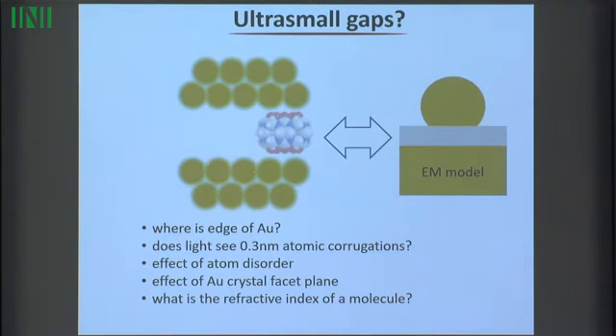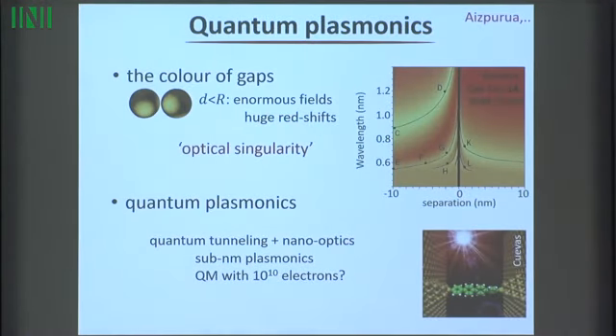Does the light see this corrugation? Gold atoms are about 0.3 nanometers apart. How should I treat that corrugation? What's the effect of disorder here? And I have one atom out of place. Should I see it? Was light trapped there more or not? What happens if I have a different crystal lattice plane here? How do I define what the dielectric constant is, the refractive index of a single molecule? Does that have a meaning? Is it just the polarizability of the molecule? Or do I have to do something else? So these are some of the problems that we're facing.